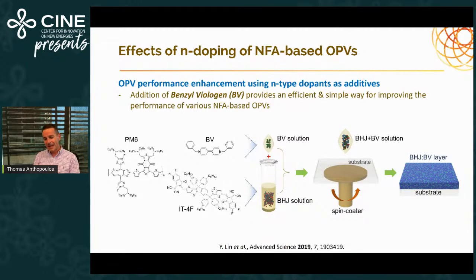on phthalocyanine. And now we had the emergence of these NFAs, and from the work we've been doing on field effect transistor, we realized a lot of these NFAs suffer in terms of electron transport due to traps. So we thought of actually introducing some N-type dopants and improve the charge transporting characteristics. And indeed, we were able to do that and reported this effect in a number of studies.